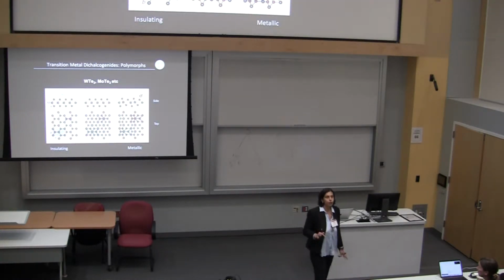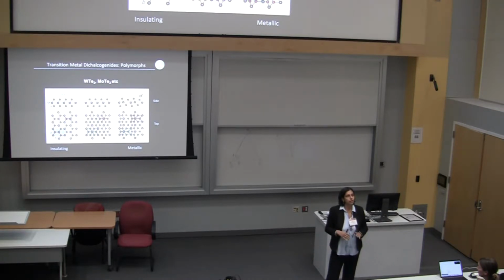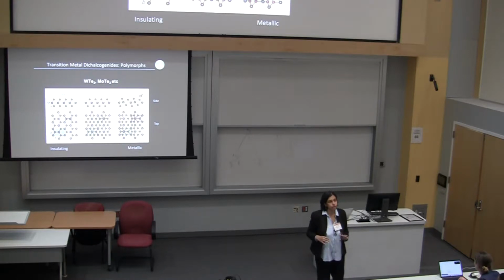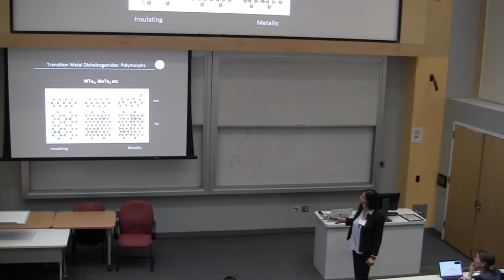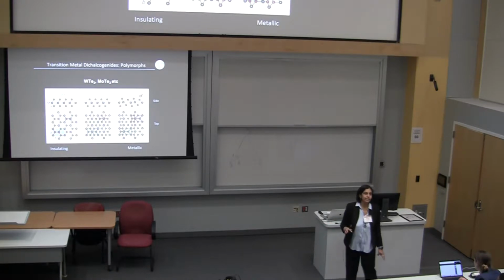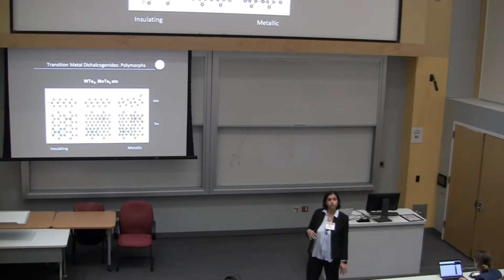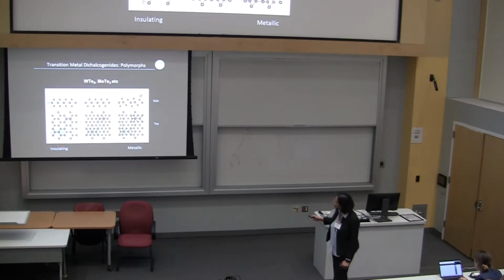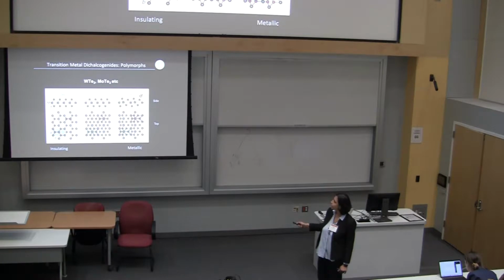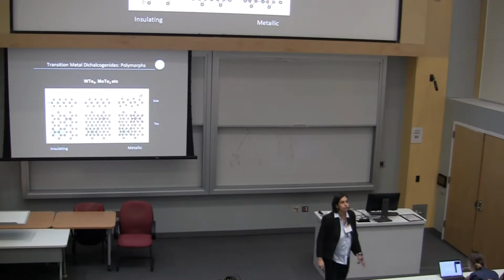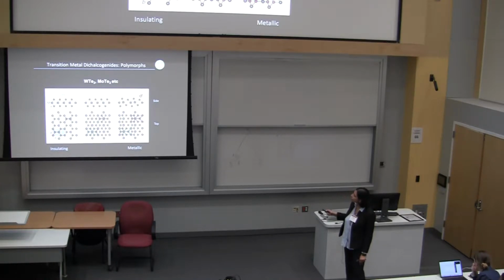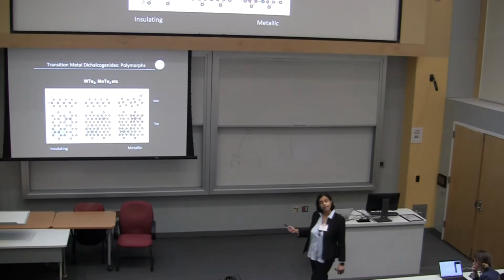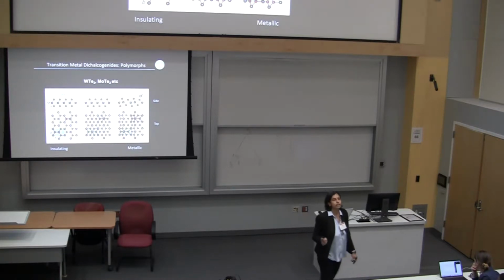So let me just briefly talk about polymorphs, because I'm going to show you some STM topography, and you can actually tell the difference between a couple of different polymorphs of these. So here's a 2H compound. This is the side view and this is the top view. If you're looking at STM, mainly what you see is the chalcogen atoms. So you'll see the selenium or the tellurium. If you look carefully, you can see that they're all arranged in a hexagonal fashion. So at least between the 2H and the 1T, by looking at STM topography, you can't tell the difference between the two, okay? However, the 1T prime is different. You can see that, for example, if these are selenium, they're arranged in an up-down fashion. And because of that, in STM topography, you'll see stripes for the 1T prime systems.